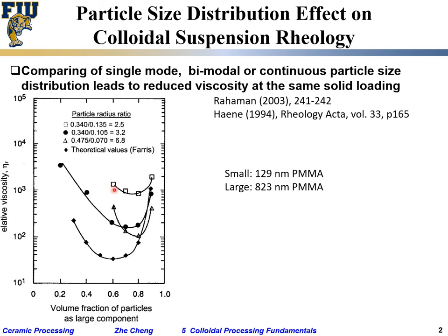Following any of these three lines — say this circle with a size ratio of roughly 3 — the viscosity is high if you have mostly large particles, and also high if you have mostly small particles, but somewhere in between there is a relatively optimized lower viscosity. This may become more complex at the extremes where the data points are cut off, and viscosity may drop further.